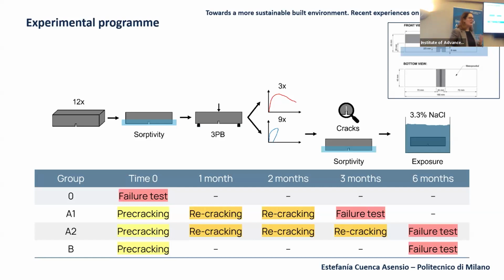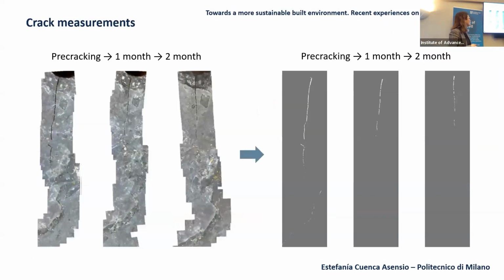So there is a lot of recracking. How does it work? We take pictures with a digital microscope and merge the images with Photoshop. Here you can see the evolution of the crack. This one is completely open because it is just after pre-cracking, then after 1 month and after 2 months. Then with binarization, quantifying the pixels, we get the area of the crack after pre-cracking and after several healing periods.